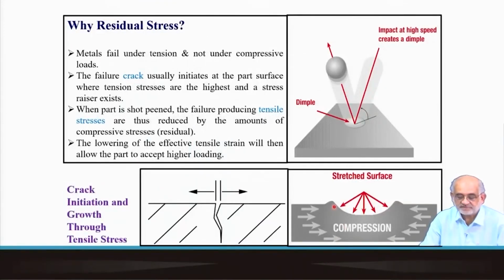So this is the mechanism that we need to pay attention to. Let's say this is a fairly magnified view, a large object, this particular sphere with certain momentum, mass and velocity hits the surface and creates a dent. That's what we expect. Now, obviously, the velocity, the mass of the material, the incidence angle, everything matters, and that will determine the amount of incident energy transferred onto the material. The surface also has to be able to withstand that energy. It should not be something like a silicate glass. It's not applicable to silicate glass or very high modulus and hardness oxide ceramics and so on, because they have practically zero ductility.